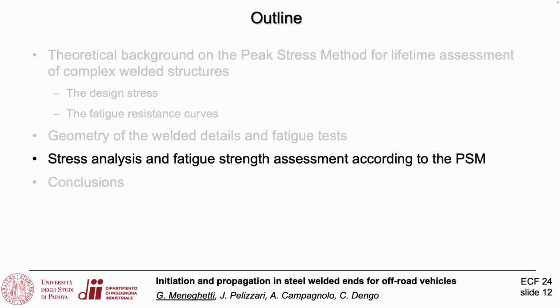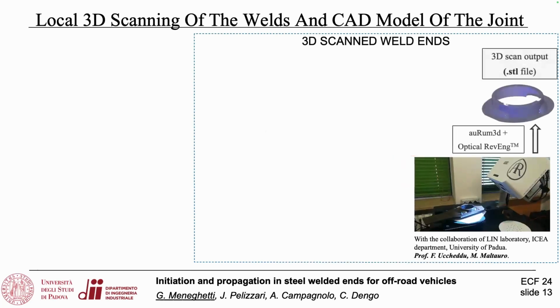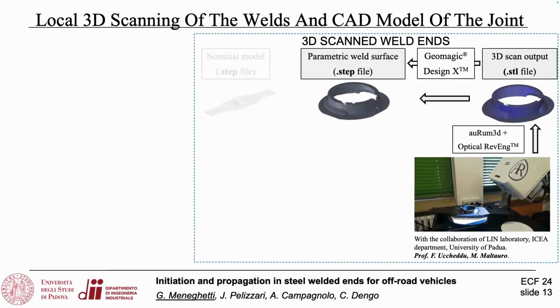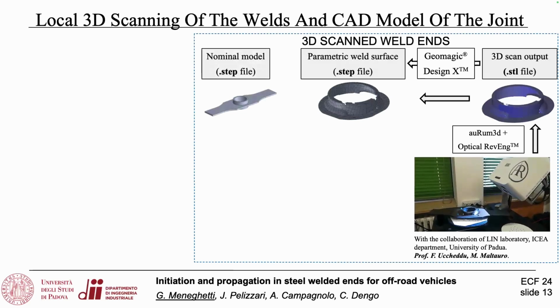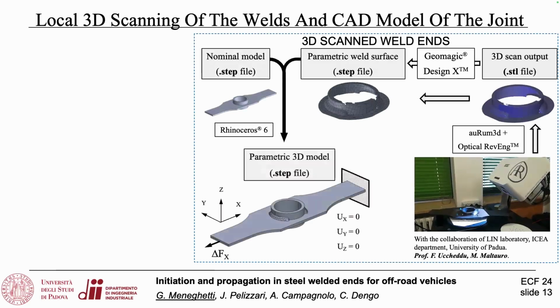Now, we want to correlate this data using the peak stress method. So we started by acquiring the real weld seams using laser scanning. You see here in the lab the laser scanning technique. We came up with a step file which was imported in the ANSYS model, and this is the complete model. We acquired all 4 weld seams and applied those weld seams to a transverse joint. This is the case of the figure, and also to the longitudinal joints.